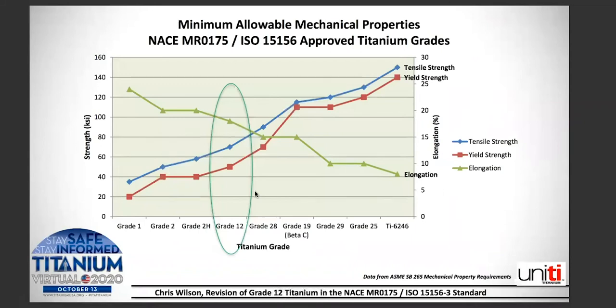Took that same data and just threw it on a chart for visual representation, and you can see that grade 12 here is right in the middle of the pack. Again, much better than grade 2, better than grade 2H as far as increased tensile strength. Not as high as some of the other alloy grades. And that data is right from the ASME SB 265 standard.